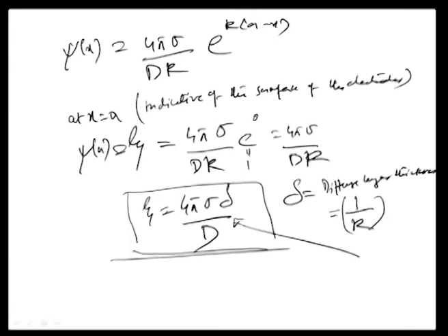This is a very critical value which matters particularly in electrochemical machining processes, because every surface would have a characteristic zeta potential with respect to the electrolyte of interest that you are flowing in, and that zeta potential has to be somehow crossed over by the applied external potential in order to be able to furnish the electrochemical machining operation. And so the zeta potential is absolutely important to be kept in mind to estimate things like material removal rate, etcetera, which happens normally during the process of electrochemical machining.